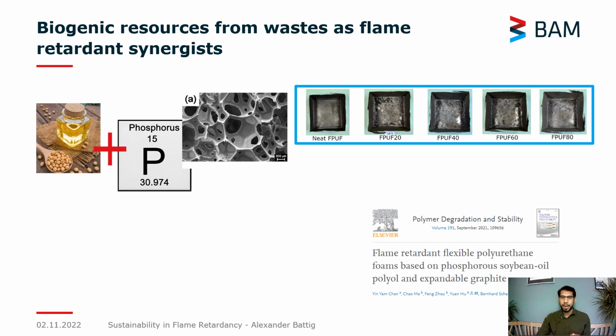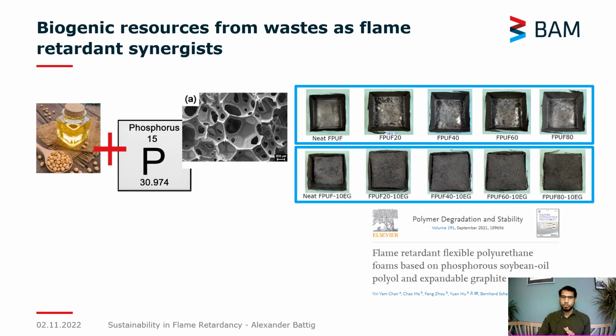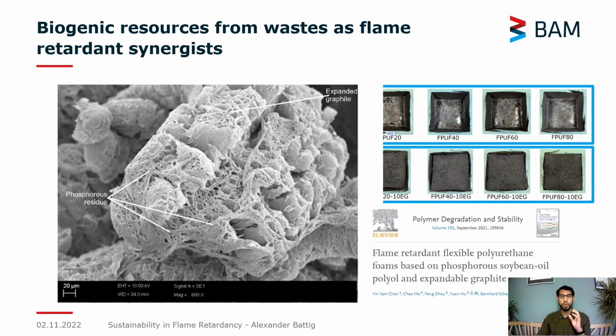However, when it was combined with expandable graphite, something really unique and interesting happened. And as you see here, by keeping the expandable graphite content constant at 10 weight%, we see a drastic increase in residue, and the morphology of the sample changed completely after fire. So what you see here is a scanning electron microscopy image, and you can very clearly see this expanded graphite material that is being glued together by this phosphorus residue. So again, there you see an interaction of this bio-based compound with another flame retardant additive inside different types of materials.